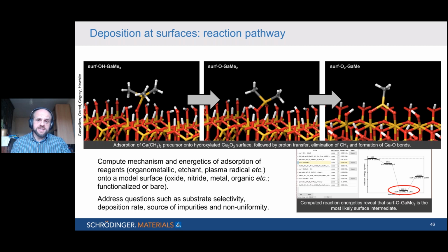It's very easy to take this sequence of reactions and look at their energies on a graph and see the reaction profile. We can see that one particular intermediate is much more energetically favorable than the others. That's the dimethyl gallium fragment in the middle. And that indicates to us maybe what kind of species predominate on the surface for long periods of time during this growth process. So this is a fairly simple reaction sequence, just to illustrate it to you.